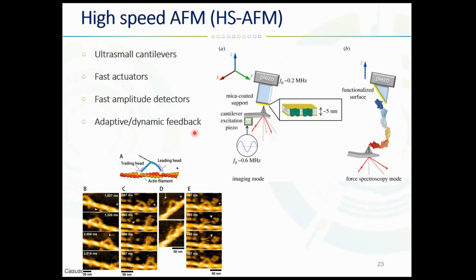The first concept was introduced about 1991 or so. And why do we need high-speed AFM? The major drawback of AFM in general is the relatively low temporal resolution, because it requires minutes to obtain a single image, and it also limits force measurements to approximately 0.1 milliseconds. So it was important to develop the high-speed AFM to detect, for example, biological processes, because one of the limiting things is time in the biological process. So a high-speed AFM allows us to visualize the conformational changes of proteins in real time, and it has been applied for a number of different biomolecules.